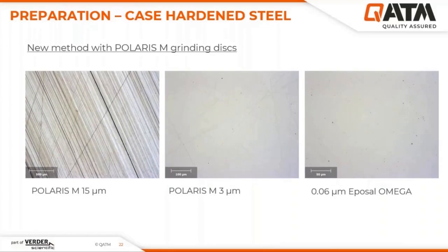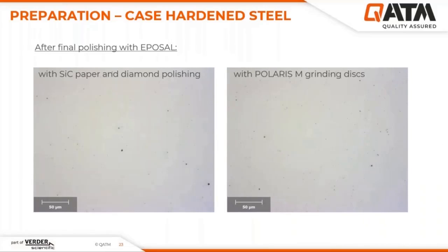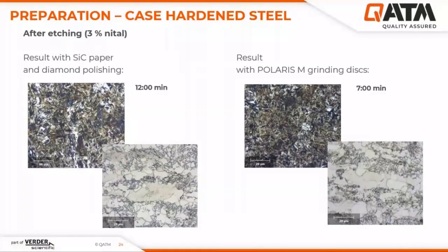In the third picture on the right, you can see the result after fine polishing with Eposal for 1 minute, so the same as before. And directly compared, the results after final polishing are really just the same. I then etched the samples, and you can see the result here. In both cases, the microstructures are clearly visible, the martensitic structure in the outer area and the original structure in the inner area of the sample. So with the new method, we can achieve a very good preparation result and on top save 5 minutes of preparation time.